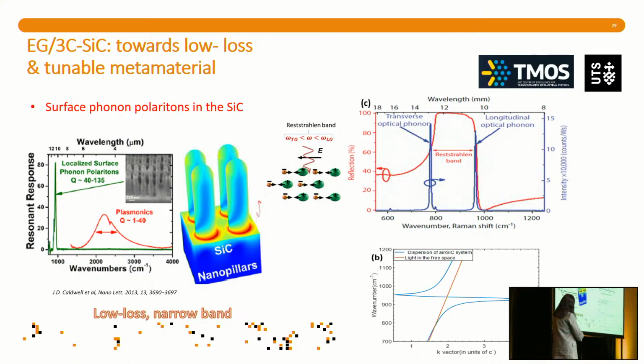Now, our collaborator, Josh Caldwell, had already done a lot of work here using silicon carbide ingots. And he had shown already that the polaritonics, basically the surface phonon in the silicon carbide, is particularly interesting because it is a low loss system. So a lot of the plasmonics works really well at visible light, but it has a lot of losses. And this is a chance to potentially have really, really low loss systems with the silicon carbide. The drawback is that we are constrained in this very, very specific window in the MIR, and there's no real way that we can change that.